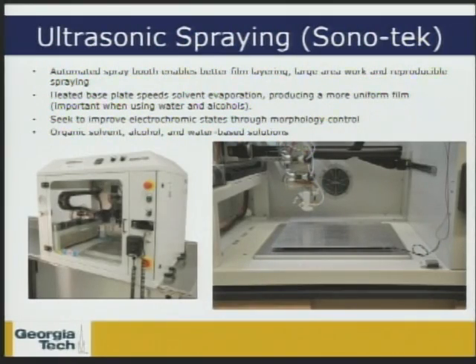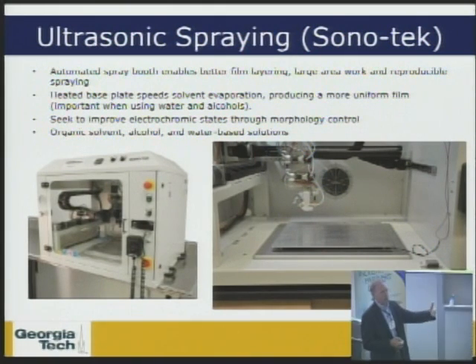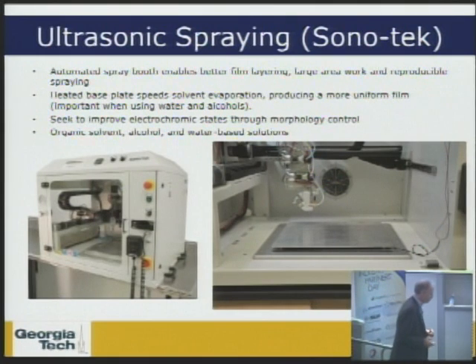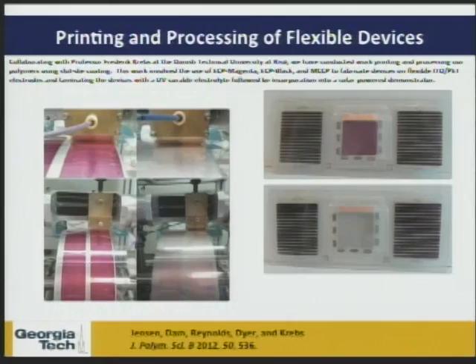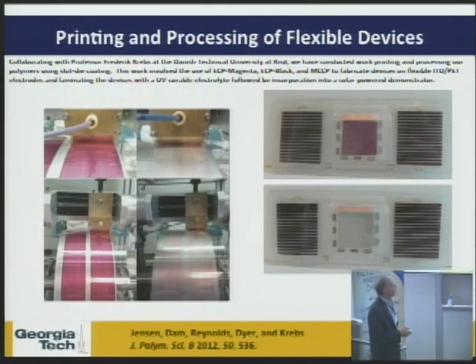What this is going to allow us to do is to put these then into windows where we want to switch our polymers that are vibrantly colored relative to this as a counter electrode, or have window systems that do not have color changes. And so with that, we've been moving over to higher levels, let's say, of processing in our lab. We've been using ultrasonic spray coating in our lab and are adding slot die coating as a processing method. Now, these are some photographs that come from a collaboration with Frederick Krebs's group in Denmark.